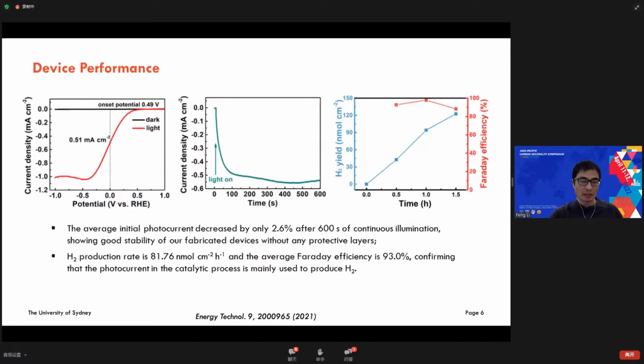We also checked the performance. Without any protective layer, it can work for 600 seconds, and the photocurrent just decreased by only 2.6%. So that means this bulk single crystal has very good stability.